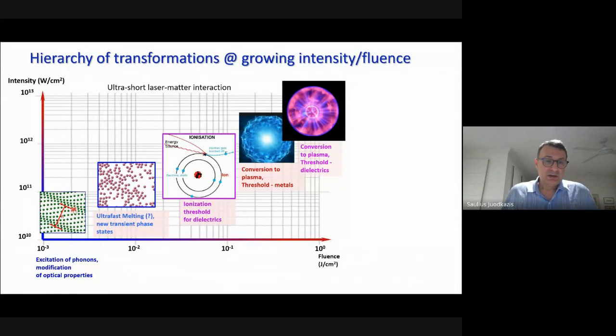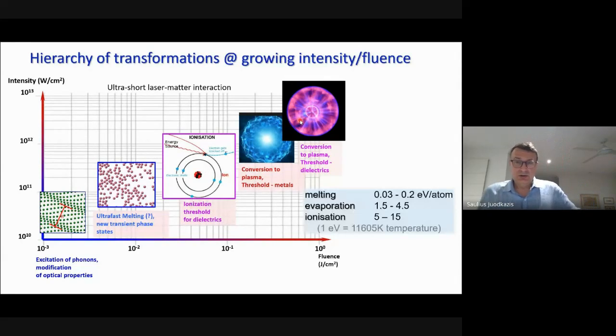We can start with the solid state material, we can heat it up, we can play with the phonon properties and resonances. But then if we increase power, we can have melting, we can have evaporation, then it comes to ionization, and we can convert into plasma, dielectric, or metal without any big difficulty. So it only depends how much energy per atom we deposited. That's why I spend a little bit of time showing that energy deposition argument, energy in the volume, which we can also calculate very well when we know the tight focusing conditions.